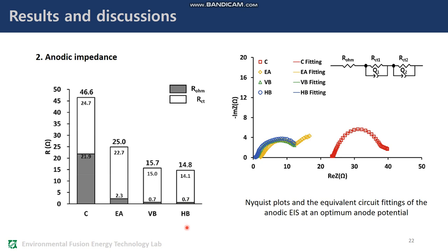Anodic charge transfer impedance occupied 95.5% in VB, 95.3% in HB, 90.8% in EA, and 53% in C for each total impedance.